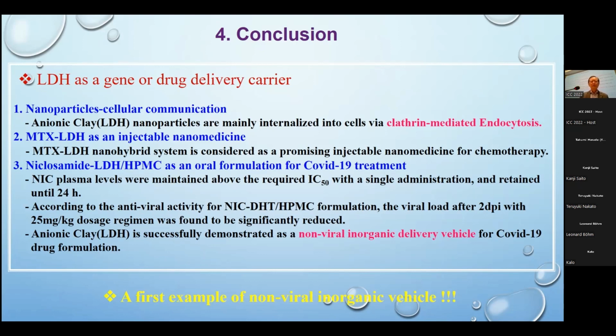We found that our anionic clay is mainly internalized inside the cell through clathrin-mediated endocytosis. We also measured the particle size dependency on this mechanism. We found that particles from 50 to 200 nanometers in size are internalized inside the cell through clathrin-mediated endocytosis. If the particle size is bigger than 250, then no such mechanism could be observed.